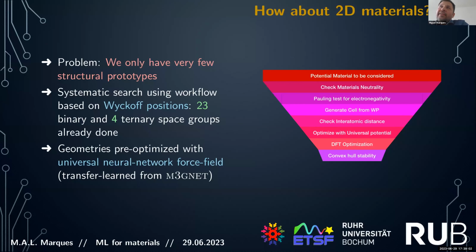And we generate in this way, in a systematic way, crystal structures that we optimize with density functional theory. And we use this as a starting point then for machine learning. Now we have a series of problems. This is, of course, not very efficient at all. One of the problems is that the systematic approach leads to structures that are often very far from dynamical equilibrium, and so it's very hard to do geometry optimizations. We again solve this problem with neural networks.